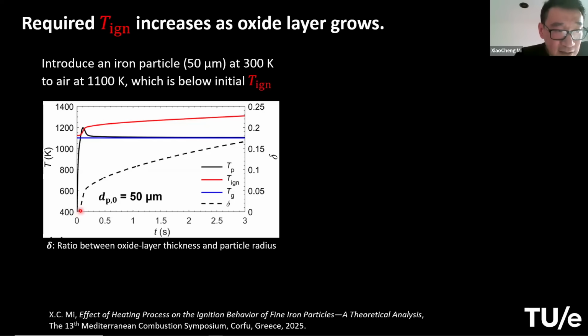But the oxide layer keeps growing, right? This delta shows the ratio between the oxide layer thickness and the particle radius. So it keeps growing. And what this red curve tells you is the temporary required ignition temperature. That means as the particle builds up its oxide layer, it requires a higher and higher temperature to ignite it. So you see this is increasing.